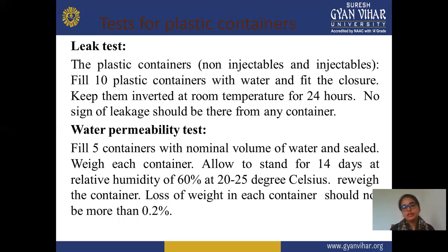Next is water permeability test. Here, fill 5 containers to nominal volume with water and seal. Each container is allowed to stand for 14 days at relative humidity of 60% and 20 to 25 degrees Celsius, and then reweighed. Loss of weight in each container should not be more than 0.2%.